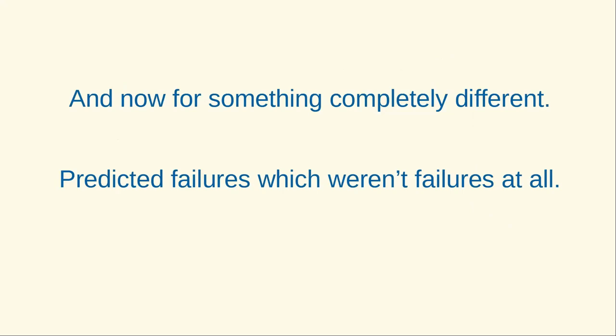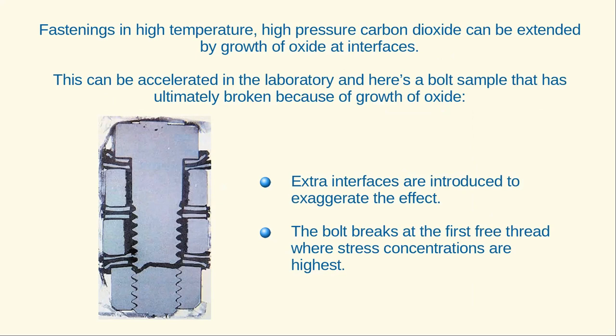And now for something completely different. Predicted failures which weren't failures at all. Fastenings in high temperature, high pressure carbon dioxide can be extended by growth of oxide at interfaces. This can be accelerated in the laboratory, and here's a bolt sample that has ultimately broken because of growth of oxide. So you've got all these interfaces, washers, nuts and everything, which exaggerated the effect. And just the growth of oxide, nothing more, extends the bolt and it breaks.